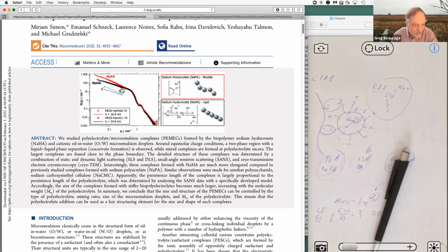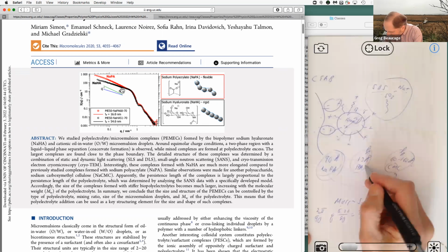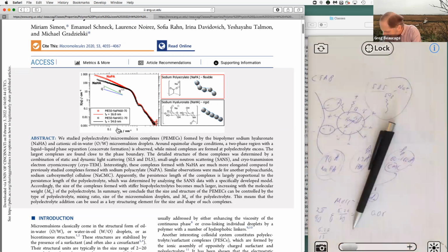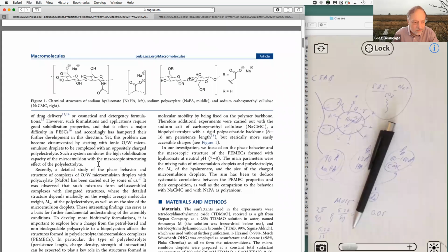And for the other one, it would be 13 angstrom. So it's like 6.28 over 13. So that's about like 0.5 or something, right? That's about half. So 2, 3, 4, 5. So that ends right about there. So the red one, the power 1 part, kind of ends right about there. So this neutron scattering agrees with the persistence length that they got from some other method. They got the persistence length from the literature, and also from light scattering in here.